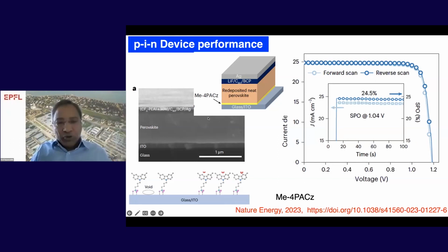Using this type of configuration, the attractiveness is that we combine the self-assembled monolayer into the perovskite solution. It means that there is an excess of hole transport material inside the perovskite composition, besides it forming a self-assembled monolayer on the bottom. So this configuration also gives 24.5% efficiency. This work appeared in Nature Energy 2023.